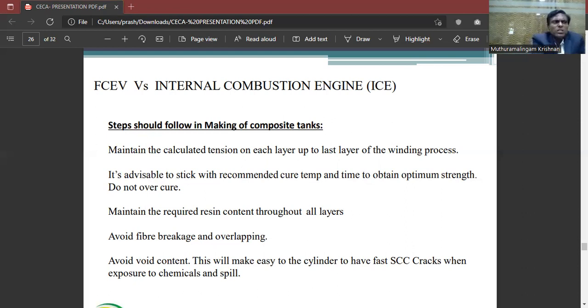So steps should be followed in making composite tanks. You need to maintain the calculated tension. The tension through each layer to the last layer has to be maintained. It is advisable to stick with the recommended cure temperature and time. To obtain the optimum strength, you have to follow the resin system manufacturer. They suggest 60 degrees, high temperature. You have to keep it for how many hours, 6 hours or 4 hours, depending on the resin system, and then maintain the required resin content throughout all layers.